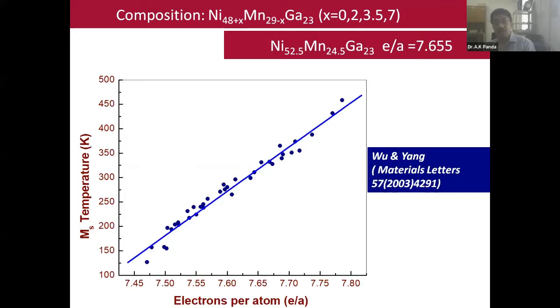And why is it important to calculate the e/a ratio, the electrons per atom ratio? Because this is how the martensitic temperature depends on the electrons per atom. Now, if you have designed something, you can read off your martensitic temperature, around 350. So you expect that below 350 you are going to land up in a martensite, and you can work with your materials. This is how you can modify your alloy compositions.